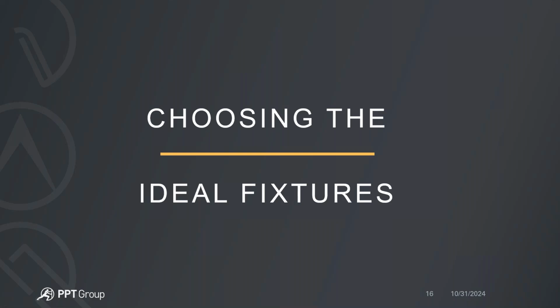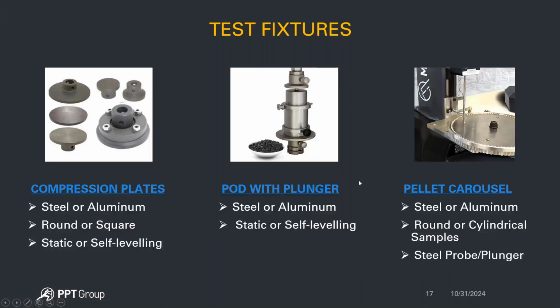All right, so choosing the ideal fixtures. Obviously, once you select your tester, the next thing is selecting the ideal fixture. And this is usually determined by which testing standard you're actually running to or what your actual testing requirements are. So if you're testing single pellets, then obviously a simple stainless steel or aluminum compression plate on the top and the bottom is sufficient, as long as the pellet is not rolling around or moving while it's under compressive load. And those plates can be either round or square.